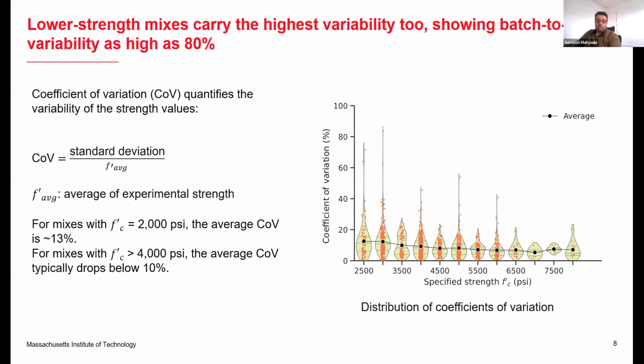But in contrast, for mixes above 4000 psi, the average coefficient of variation typically drops below 10%. This is primarily because of the better quality control in these more costly productions.